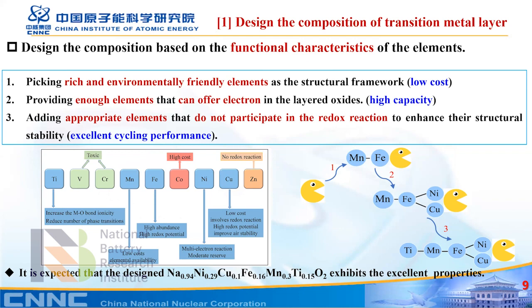The first work is designing the composition of the transition metal layer, considering the different roles of different elements. So here is our roadmap. Firstly, for low cost, we choose manganese and iron because they are rich in reserves and environmentally friendly. Secondly, we use nickel and copper to replace some iron because they can provide enough electrons to help achieve high capacity. Thirdly, we add some titanium to stabilize the structure because titanium doesn't participate in the redox reaction. So we designed and prepared a positive electrode material with sodium, nickel, copper, iron, manganese, titanium, and oxygen. We hope this material will show much better performance.